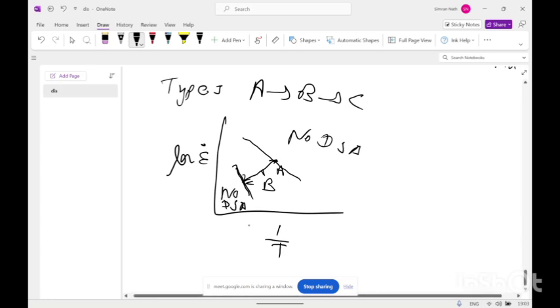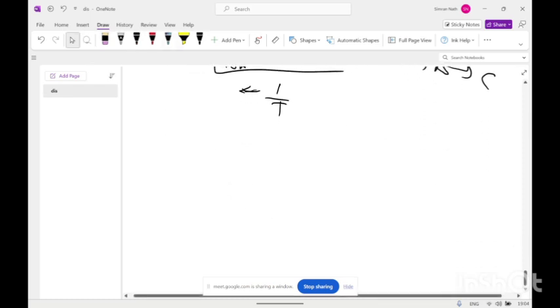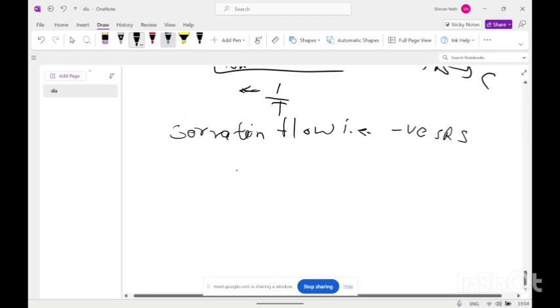So with increase in temperature, the shift of deformation flow changes from A, B and C. So with increasing temperature, the changes in serrated flow follows this path A to B to C, and this point is C, and in this region there is DSA. So the serrated flow is always associated with the negative strain rate sensitivity, means with increase in strain rate, stress decreases.